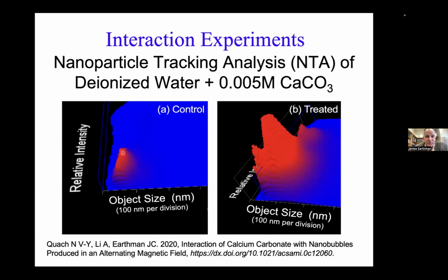If we take deionized water and just put calcium carbonate in it, we would get one peak in the object size. This is at the solubility limit of the calcium carbonate, very low, 0.005 molar. And we get one peak in relative intensity. We get one peak in object size, what you'd expect with just calcium carbonate.